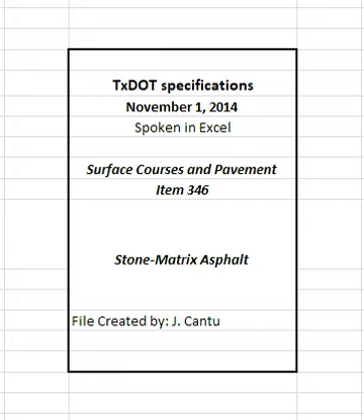4.9.2.4.1 Gradation. Suspend operation and take corrective action if any aggregate is retained on the maximum sieve size shown in Table 7. A sublot is defined as out of tolerance if either the engineer's or the contractor's test results are out of operational tolerance. Suspend production when test results for gradation exceed the operational tolerances for 3 consecutive sublots on the same sieve or 4 consecutive sublots on any sieve unless otherwise directed. The consecutive sublots may be from more than one lot.